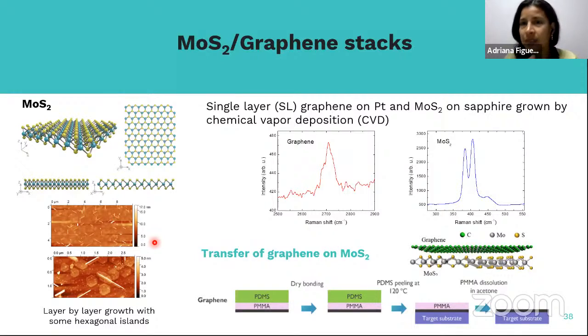These materials are also like the group 5 materials and so on. So it has been established, a very nice protocol. If you manage to have a good MBE system to control the temperature of the growth, I mean, to control the temperature not only of the cells but also of the substrate, which is what you usually have, it's a nice system, and then you manage to get very nice and controlled growth of the layers. So yeah, it's good. Thank you.